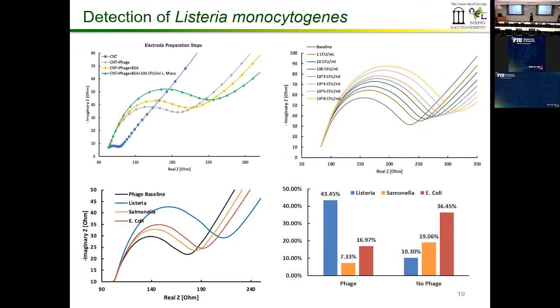These are the selectivity studies. You can see when you don't have any phage on the surface, your target is Listeria, and the electrode actually doesn't measure Listeria significantly. It measures E. coli better. But when you have the phage, you can see it is selecting Listeria as its target. So it provides the selectivity when you have the phage. So that's the demonstration of these two graphs.